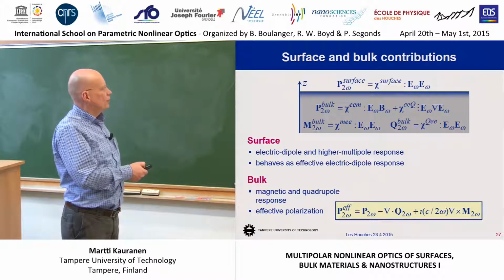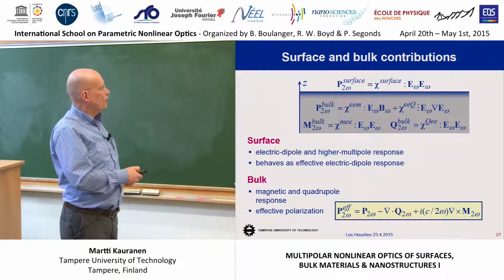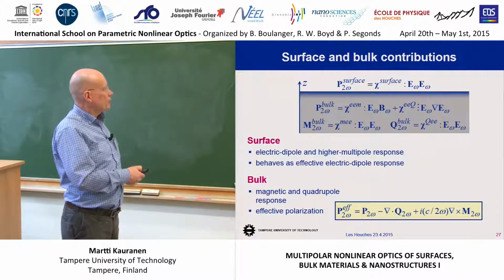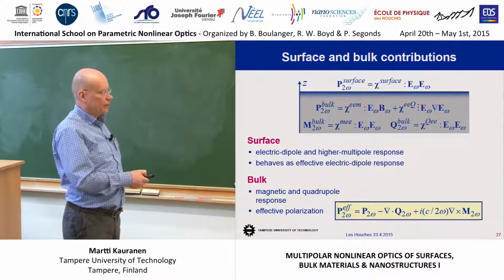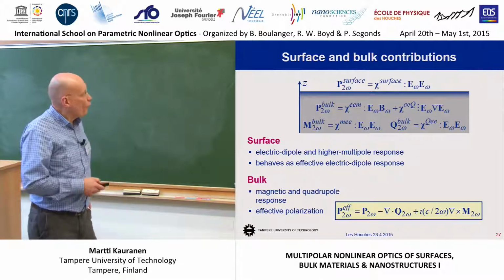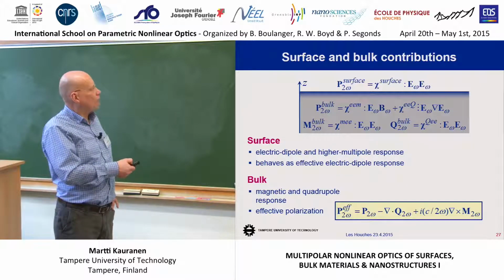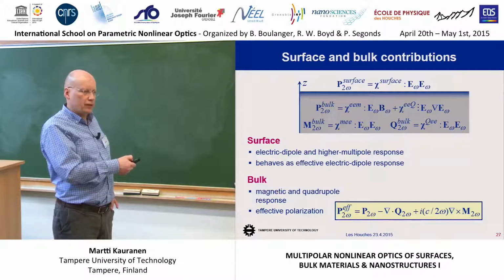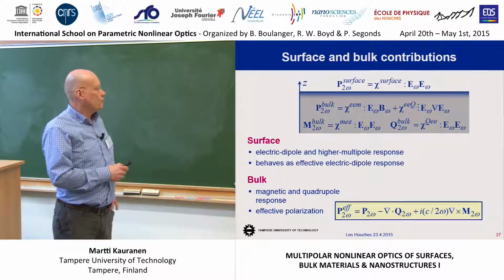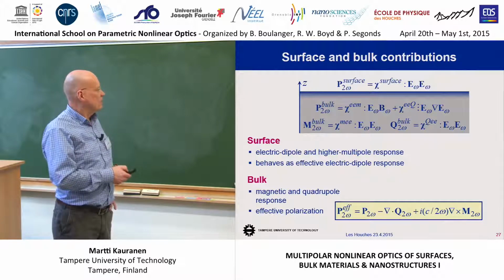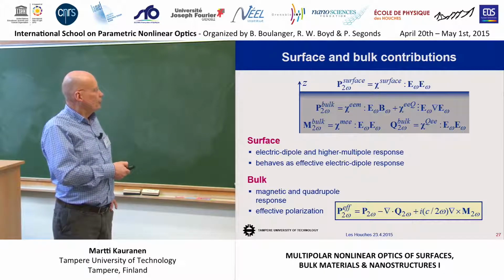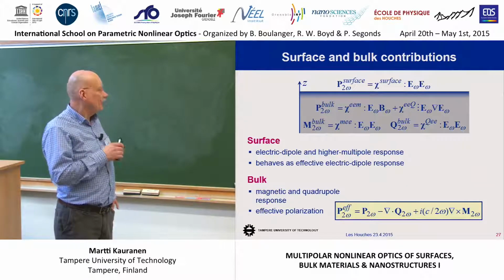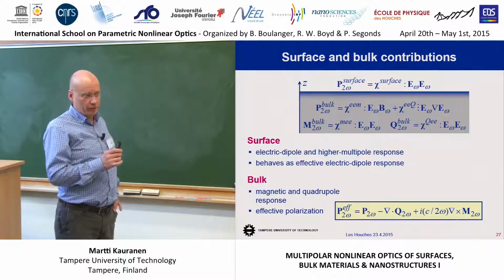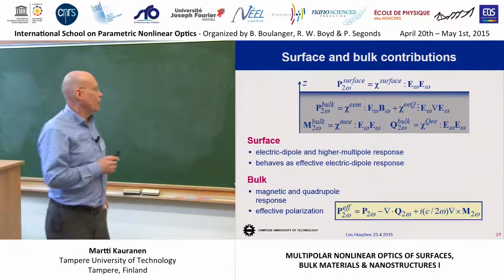But we can have secondary polarization due to this EEM tensor and EEQ tensor. And then furthermore, in principle, we could have this nonlinear magnetization from the MEE tensor and nonlinear quadrupolarization from the QEE tensor. These are the tensors we defined earlier. Of course, in principle, it's possible that we would have some other type of multipole response at the surface region also, but it depends on how you describe that. It turns out, however, that whatever happens at the surface can be included in the effective electric dipole response, at least within the present knowledge.